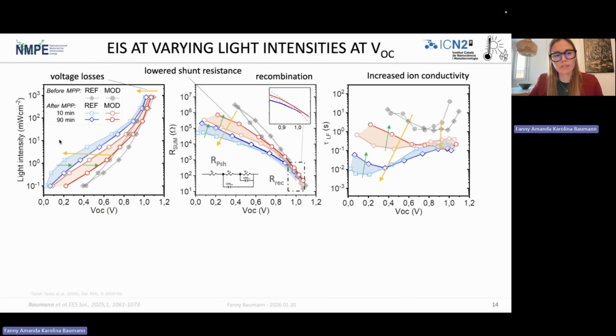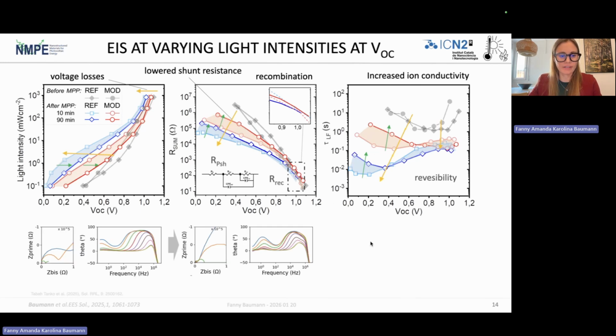reversibility here as well, because what you can see is that devices measured 10 minutes after the operational stability test in the slide are having a much larger change than devices measured 90 minutes after. I'm going to show you another example of that further on. So this reversible component seems also really more prominent at the lower light intensities.